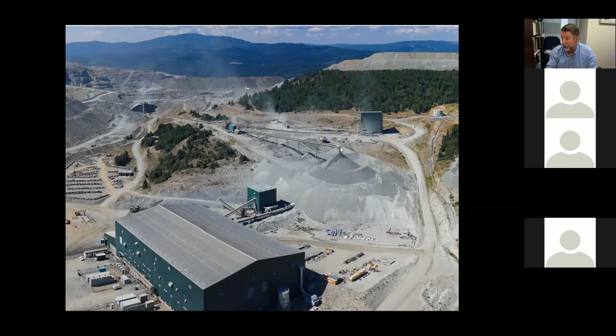If this is out, we can still feed straight to the coarse ore stockpile. But when this is operating, which is almost all the time, this now becomes essentially almost a fine ore stockpile. As you can see here, the stockpile size is 200,000 tons, which essentially allows for 5 days of production. Although that has not been tested yet, but that's the design. And this is the pebble crusher that sits just outside the mill on a continuous circuit. And now we'll take a look at the inside of the mill.